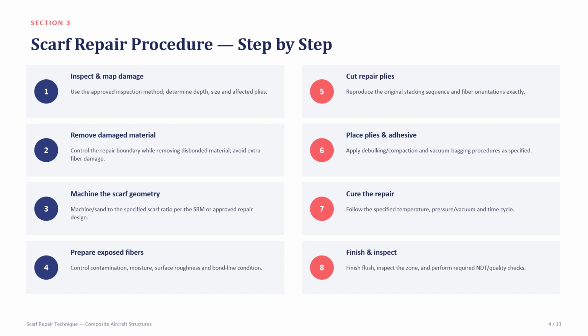And what is the procedure for scarf repair? The step-by-step procedure. First, inspect and map damage. We have to use an approved inspection method and determine its depth, size and affected plies. And second is to remove the damaged material. Control the repair boundary while removing disbonded material, and avoid extra fiber damage. And third one is machine the scarf geometry. Machine or sand to a specified scarf ratio per the SRM or approved repair design.